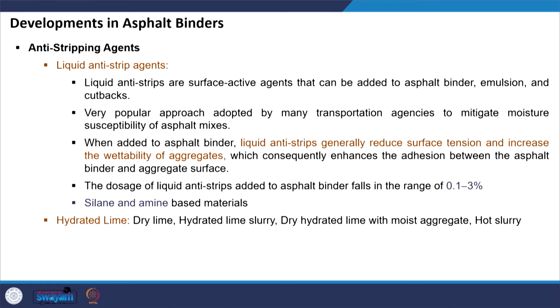We also have anti-stripping agents. These are used to resist moisture damage in the asphalt mixtures. Again, anti-stripping agents can be of different types. Commonly, liquid anti-stripping agents are used. These liquid anti-strip agents are surface active agents that can be added directly to the asphalt binder, to emulsion, or also to cutbacks if we are talking about cold bituminous mixture as well. These are very popularly adopted by various transportation agencies to mitigate moisture susceptibility of asphalt mixtures.